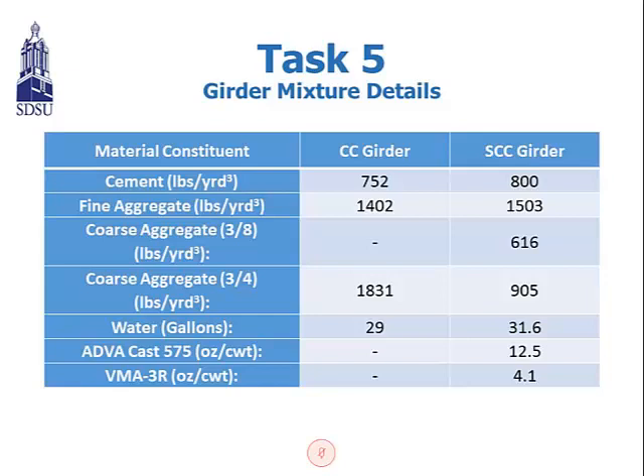For the SCC girder, following the established SCC mixture guideline, we chose cement 800 pounds per cubic yard, fine aggregate 1503, coarse aggregate 616, coarse aggregate 905, and water 31.6 gallons. And to compare the SCC structural performance against that of the CC girder, we also fabricated a normal concrete girder. You can see the details for the mixtures for the CC girder.